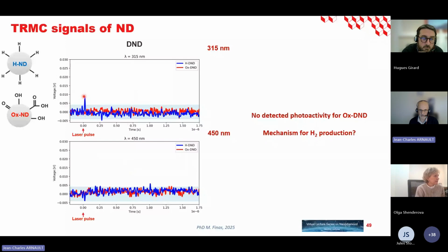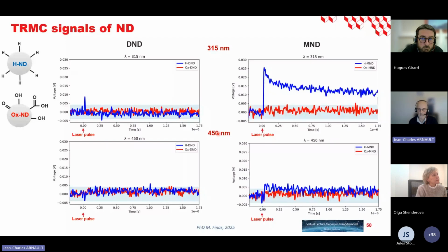The only signal we can measure concerns the hydrogenated detonation nanodiamond. This is the signal you can see here. This is reproducible. We have reproduced it on several samples. But you can see that carriers probably recombine very quickly, because you don't have this behavior shown for the TiO2 before. So what happened when we switched to the milled nanodiamond? This is what we got for the milled nanodiamond in the UV and in the visible range for the two surface chemistries. For this particle, the oxidized particles cannot show any photoactivity. But if you look at the hydrogenated one in the UV range, you see the typical signal of a semiconductor. This looks like the TiO2 signal I showed before. So this means that in that case, we really have the semiconductor behavior we expect in the UV.